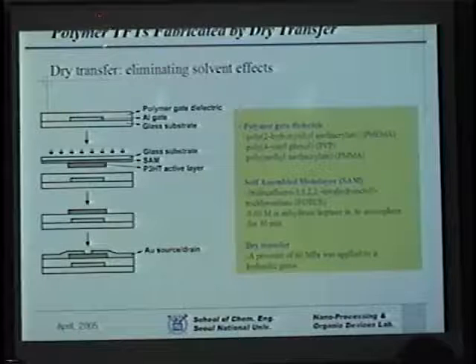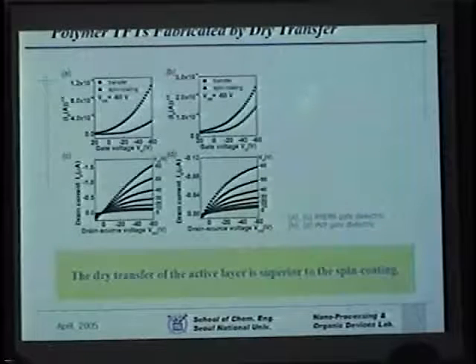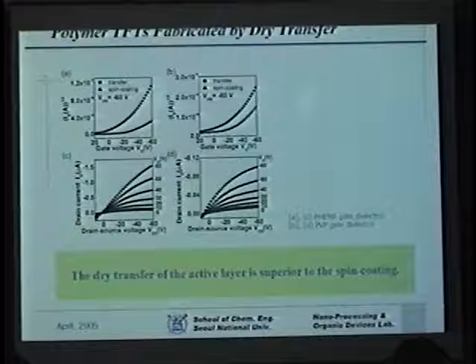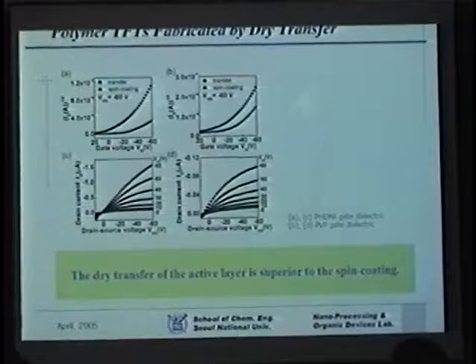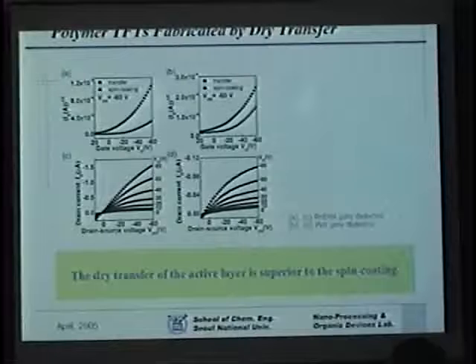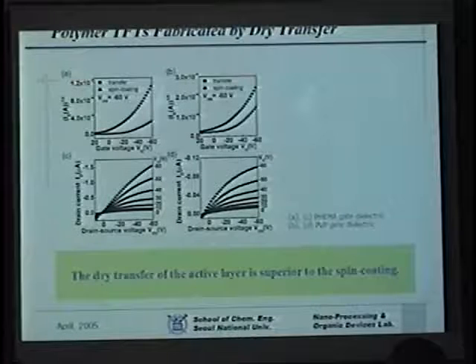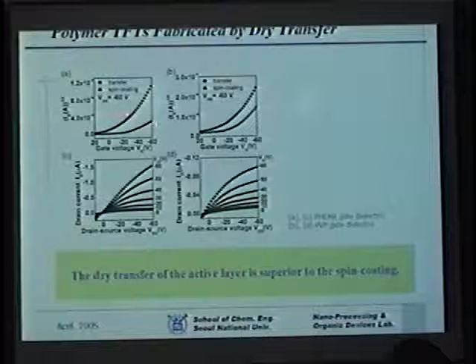And the last one, I'll just move on, utilizes dry transfer. In this case, you transfer the active polymer semiconductor layer onto the underlying dielectric. As a result, by doing the dry transfer, you eliminate the bad effect of solvents. And if you want to, before transfer, you can make the surface hydrophobic. And also, if you like, you can do annealing as well. And as you can see here, with PHEMA as gate dielectric, compared with the direct transfer method and the solution technique,